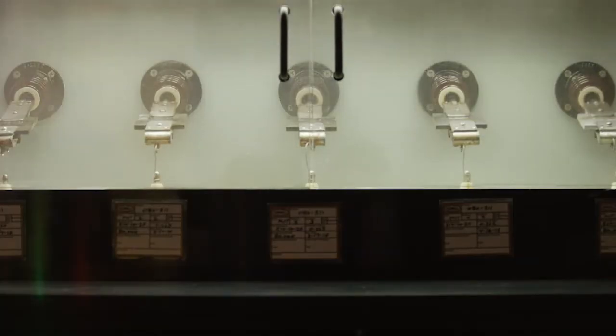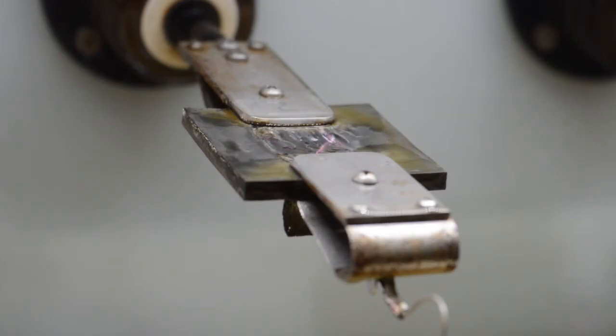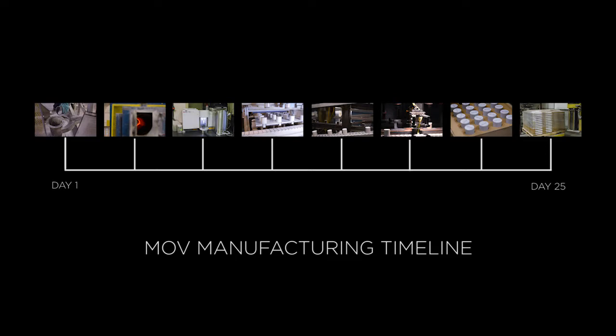Today, Hubbell engineering teams fully control the design and manufacture of MOV discs in close proximity to the design and development of the arrestors they make up. Even before the first step of production, incoming raw material batches must be tested to match supplier certifications. The purity content, contaminant level, particle size, surface area, and crystal structure are all critical characteristics which must be known before manufacture.